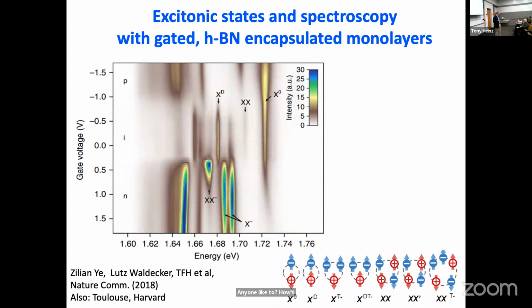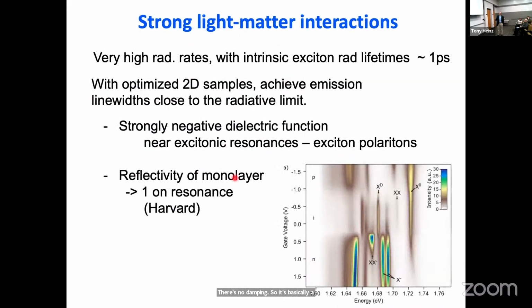Pardon me? It would get reflected. Yes. So it's sort of like there's no damping. So it's basically an infinite response. And that was recently shown in a nice paper by Hung Park and collaborators, and they didn't get 100% reflectivity, but it was actually getting pretty close to 100% reflectivity. Basically, radiatively broadened means there's no other damping in the system, so it's like an infinite conductivity. And under those circumstances, you get 100% reflectivity.